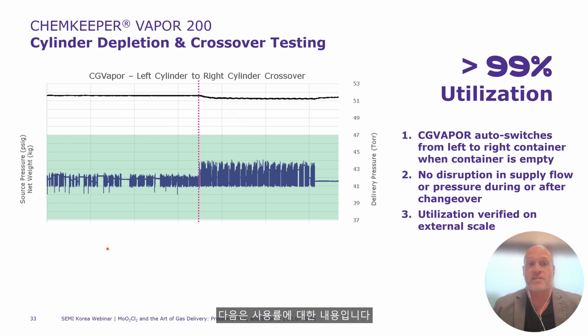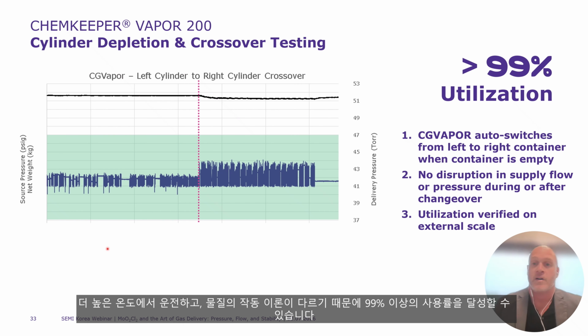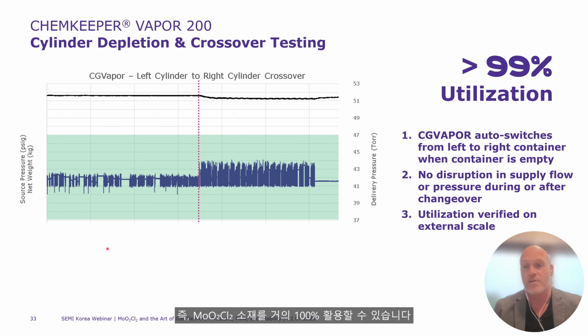And this is really utilization. Because we're at higher temperature operation, because of the fundamentally different theory of operation of our material, we're able to get to greater than 99% utilization. We're using almost every molecule of molybdenum dioxide dichloride in there. We're not leaving 5, 10, 20% on the table.